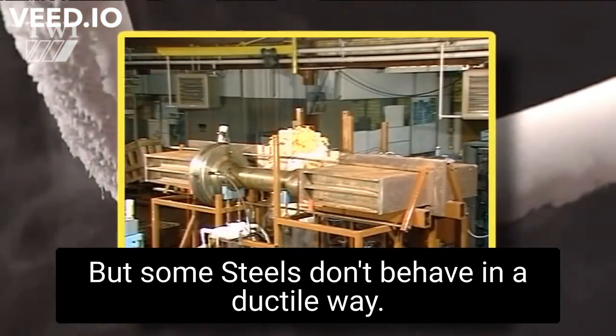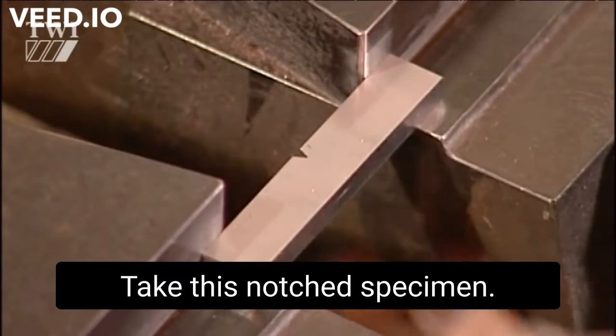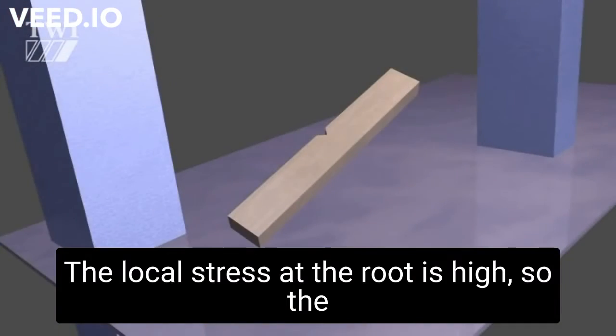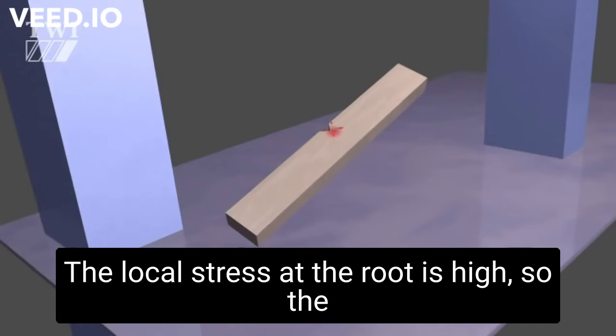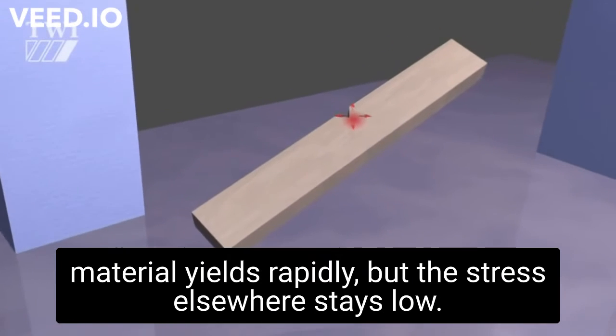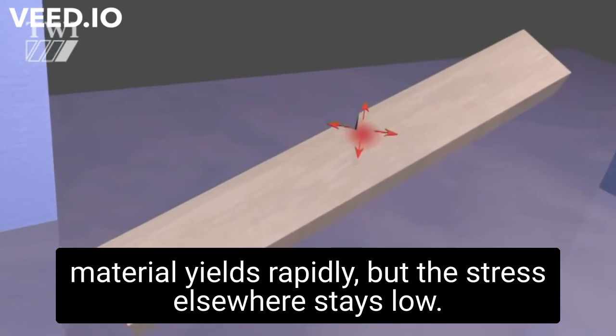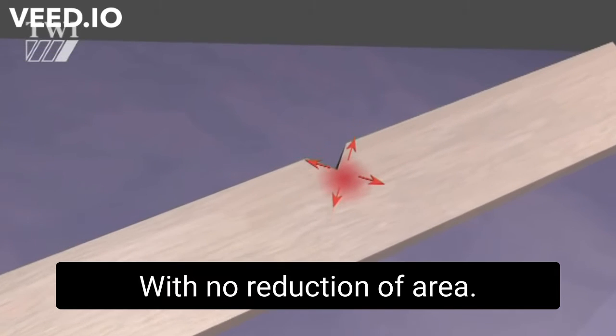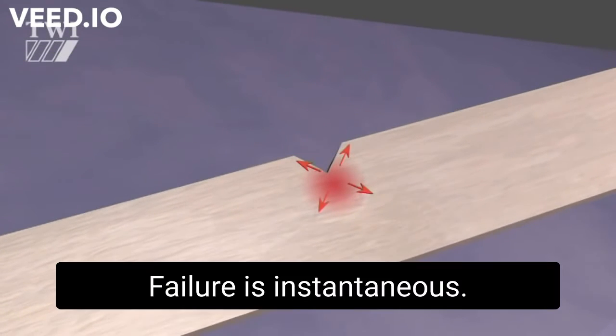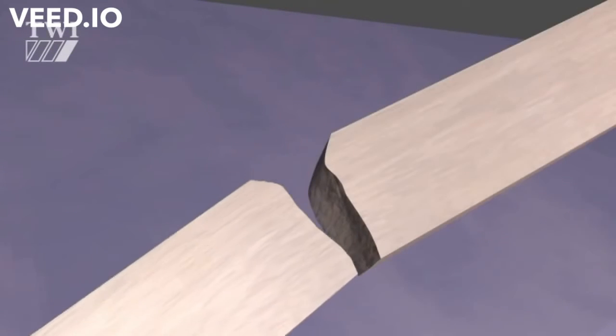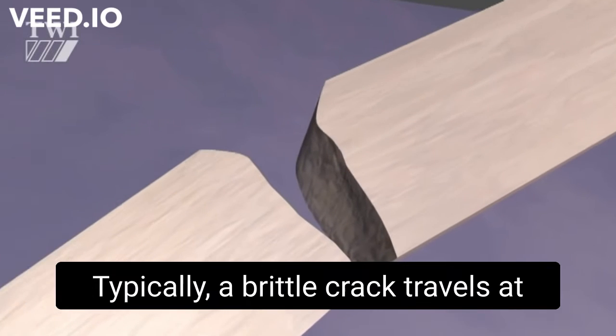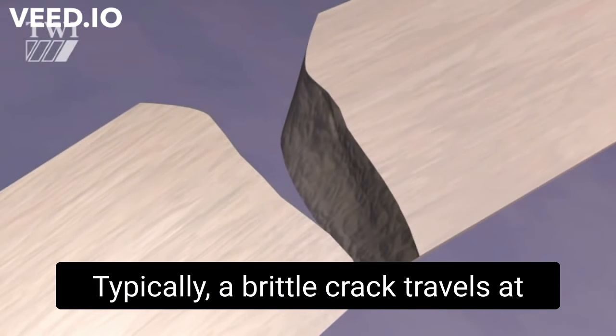But some steels don't behave in a ductile way. Take this notched specimen. The local stress at the root is high, so the material yields rapidly. But the stress elsewhere stays low. With no reduction of area, failure is instantaneous. There's no warning. Typically, a brittle crack travels at more than 1 kilometre a second.